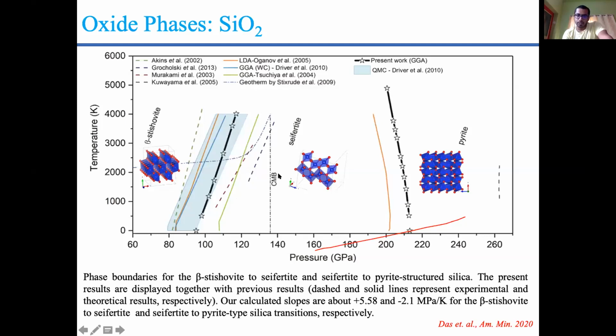Now we concentrate on this negative slope. There was a previous study which did the same calculations with LDA, and they found a 10 GPa lower transition but almost the same slope. But they never explained why the slope is negative. So the point is, we explained why this slope is negative. As we are going to a high pressure transition, our volume change is always negative, and the Clapeyron slope is given by the change in entropy over the change in volume.